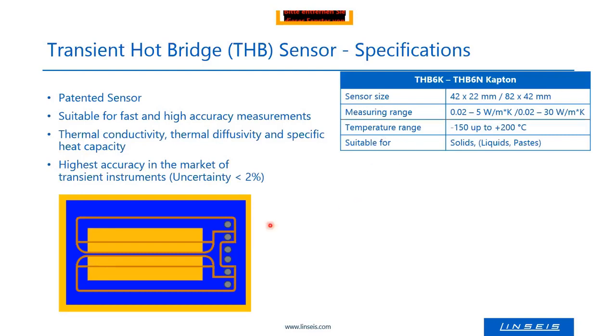The thermal conductivity range for these THB sensors is from around 0.02 up to 30 watt per meter Kelvin. In this range, we have the highest accuracy, below 2%. And the Kapton sensors can measure up to 200 degrees Celsius. If a furnace with inert gas atmosphere is available, they can withstand also 400 degrees Celsius. And it can be applied for solids, liquids, and pastes.